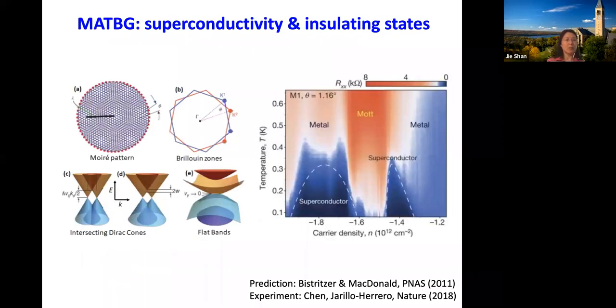So here's an excellent example from twisted bilayer graphene, this pioneering work from Pablo's group, and a prediction from Allan MacDonald almost 10 years ago. We have seen this many times, I'm pretty sure. At this twist angle, the interaction between the two layers is so strong, the Moire potential I mentioned can be big, and then you make a flat band. And we have seen remarkable phenomena such as superconductivity, insulating states, and later development of some topological phases as well. So this is not what I'm going to discuss today.